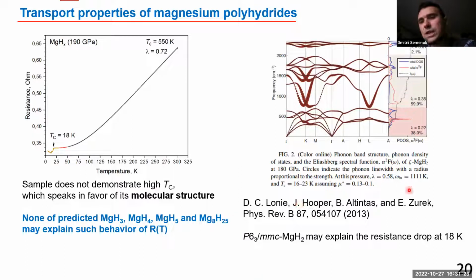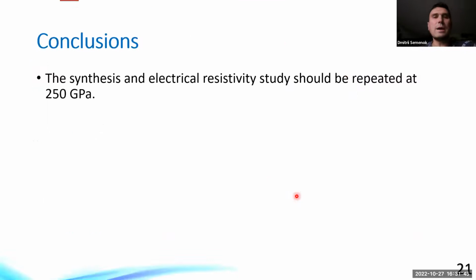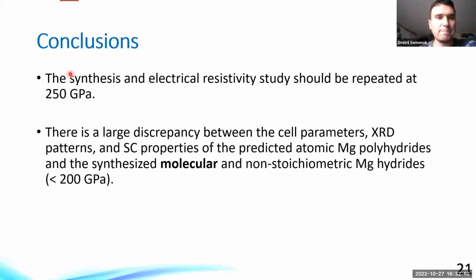But again, according to theoretical prediction, it should have a much higher logarithmic frequency, but the experimental Debye temperature and logarithmic frequency are almost two times lower, so I'm not sure that this is magnesium H2. We need to think about it more. Okay, so what do we plan to do? We plan to repeat the synthesis and electrical resistivity study of magnesium hydride at higher pressure, because at higher pressure we expect that the molecular hydrogen sublattice will transform to an atomic hydrogen sublattice, and we have a chance to see superconductivity.